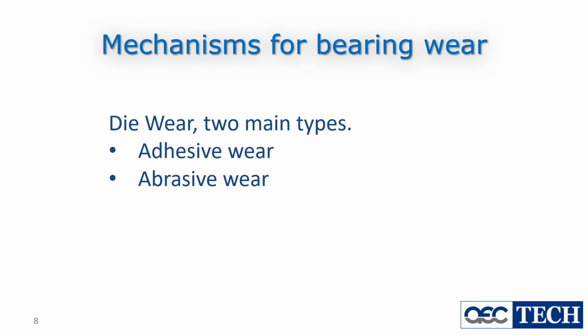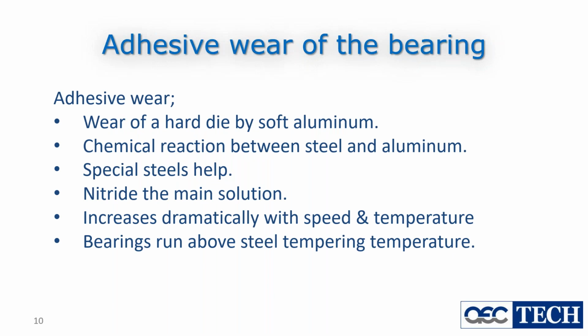So when the aluminum is passing through the bearing, the soft aluminum is passing and it's carrying with it those abrasive hard particles. So they will do like a sandpaper. It will do abrasive wear. But the aluminum itself, which is soft, how it wears, which is the main type of wear in the bearing, is adhesive wear, which is done by soft aluminum. So why does it do that? Because aluminum adheres to the iron, and in the next slide I'll show how much more adhesive it is compared to other metals with iron.